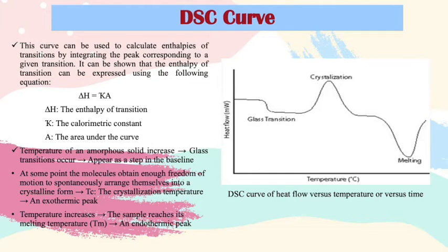This transition from amorphous solid to crystalline solid is an exothermic process and results in a peak in the DSC signal. As the temperature increases, the sample eventually reaches its melting point, Tm. The melting process results in an endothermic peak in the DSC signal. The ability to determine transition temperatures and enthalpies makes DSC an invaluable tool in producing phase diagrams for various chemical systems.